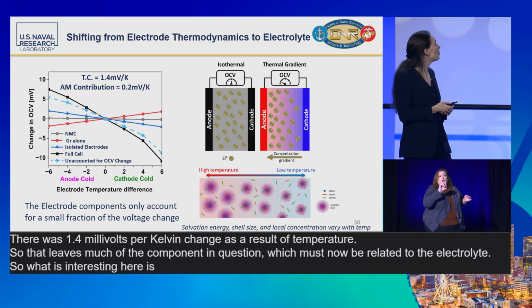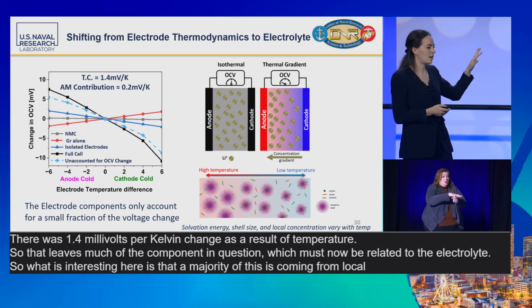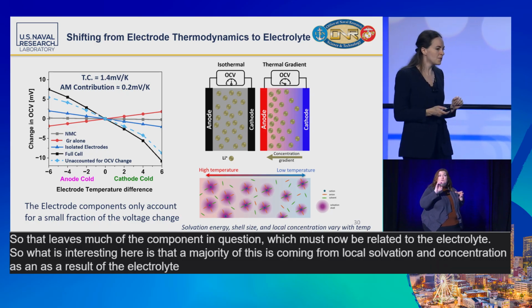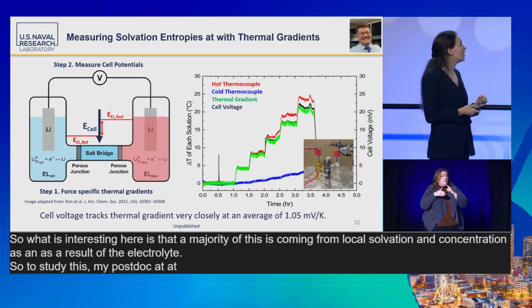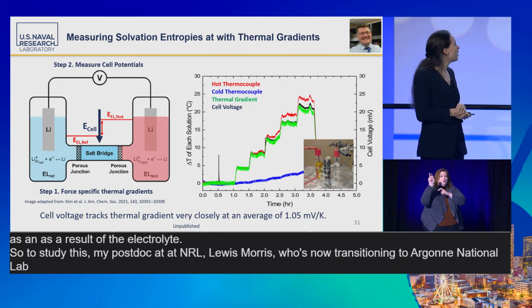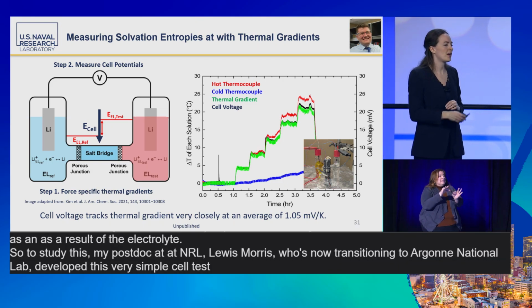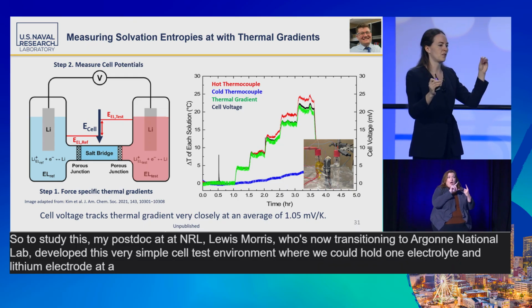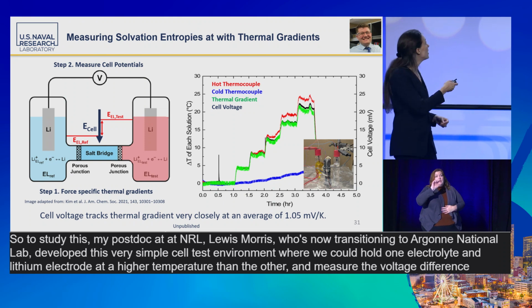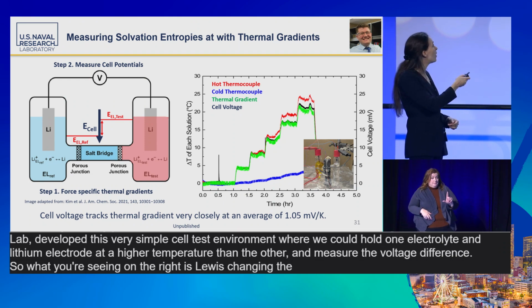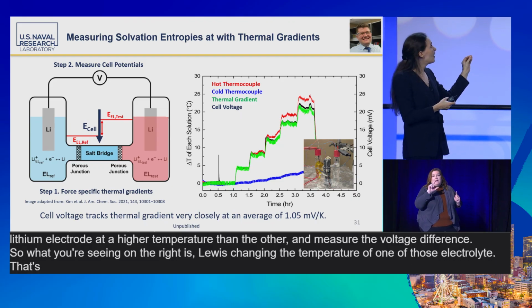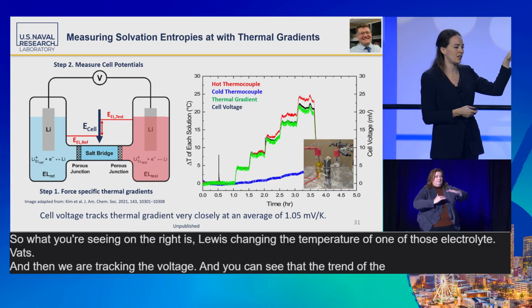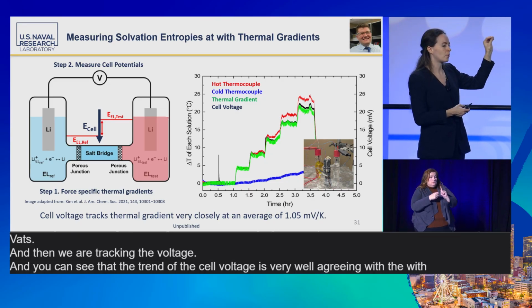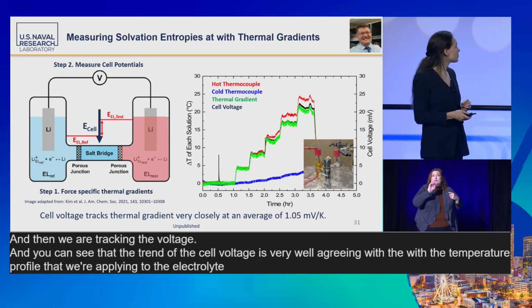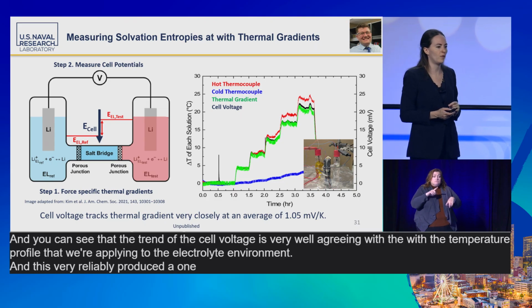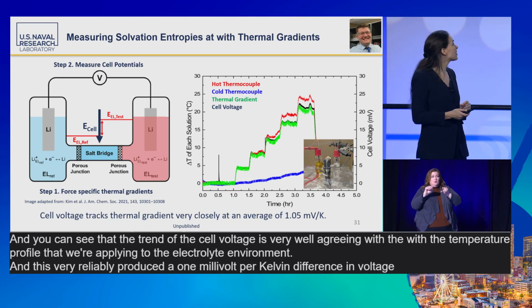So what is interesting here is that a majority of this is coming from local solvation and concentration as a result of the electrolyte. So to study this, my postdoc at NRL, Lewis Morris, who's now transitioning to Argonne National Lab, developed this very simple H-cell test environment where we could hold one electrolyte and lithium electrode at a higher temperature than the other and measure the voltage difference. So what you're seeing on the right is Lewis changing the temperature of one of those electrolyte vats, and then we are tracking the voltage, and you can see that the trend of the cell voltage is very well agreeing with the temperature profile that we're applying to the electrolyte environment. And this very reliably produced a 1 millivolt per Kelvin difference in voltage across those electrolytes.